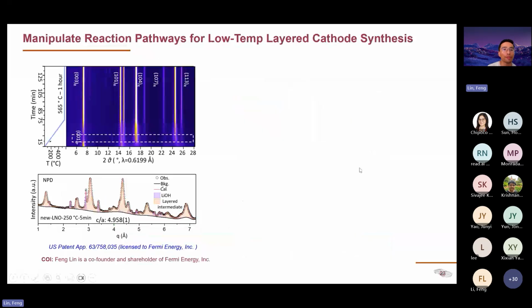But we recently started to manipulate the reaction pathways for low temperature layer synthesis. I could not go into too much detail on that, but comparing the X-ray diffraction that you are seeing here versus the neutron diffraction data that I've shown earlier, you start to see that the phase change is much smoother and initiated at much lower temperature already. You start to see the layer phase formation. And here is the temperature at 250 degrees C for only 5 minutes.